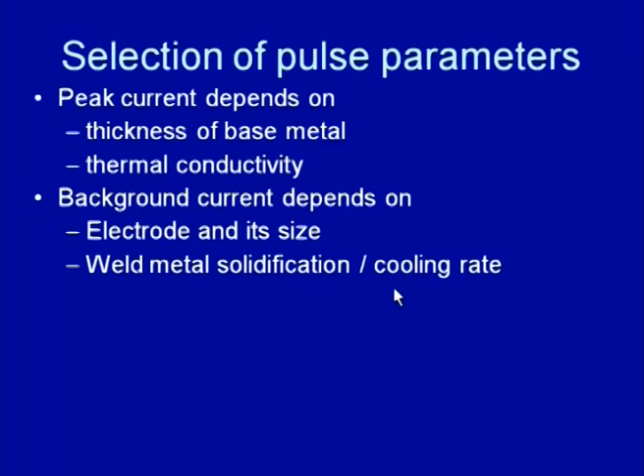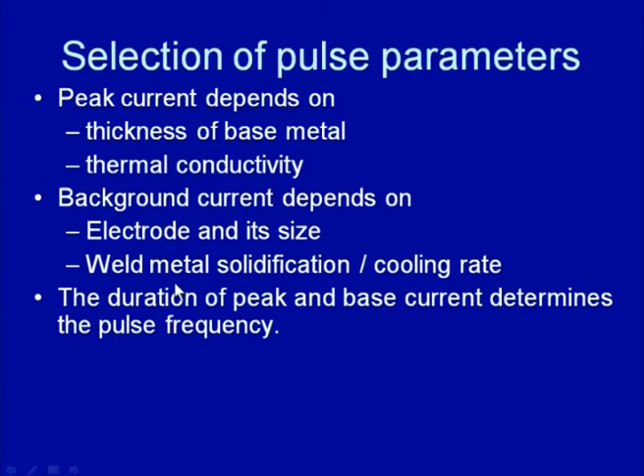The desired weld metal solidification and cooling rate also determine the base current value. Sometimes an excessively long base current period causes a high cooling rate, and due to the high cooling rate gas entrapment takes place, which in turn leads to development of porosity. A ratio between the peak current and the base current is always maintained. The duration of the peak current and base current determines the pulse frequency.